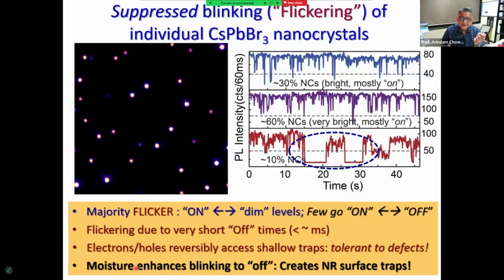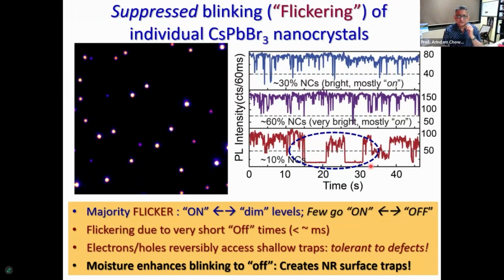What we found out is that when we introduce more and more moisture, these kinds of long off states, or real blinking behaviors, start popping up. So that means this moisture or oxygen from the atmosphere can create some sort of surface traps which are non-radiative in nature. Okay. Now going back to extended structures.